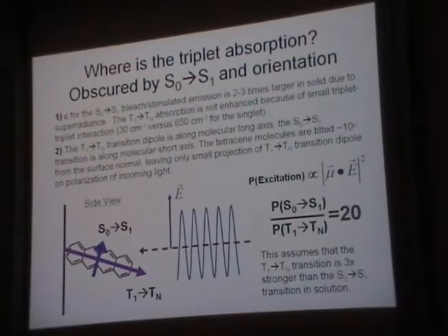Now the S0 to S1 transition, the one that gives rise to superradiance, the one that creates these exciton states that I keep talking about, is exactly perpendicular to the molecule's long axis, right? It's counterintuitive, I guess. The triplet to triplet transition is parallel to the long axis. So when the light comes in, it's the dipole selection, it's mu dot E. Well, E is going to be somehow parallel to the substrate because I have to shoot my light at the substrate, right? So the parent polarization is going like this. And when I try to dot my mu vector into that, I'm not going to have very good success with the triplet. But it's going to go great for the singlet, right? That's going to have a very nice, strong interaction.